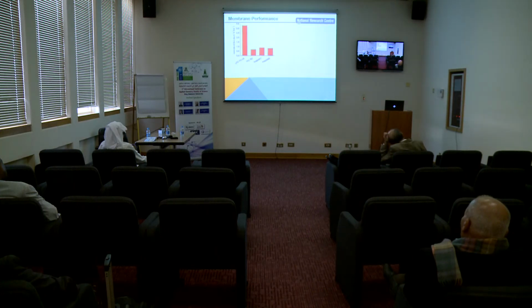The surface properties were also investigated using zeta potential, and here we can see that the membranes with polyamidoamine 1 and 2 have a higher pH value, which means that we have more amine groups on the surface. And we also investigated the contact angle using the air captive bubble method, and we can see that the UTC 70, which is a commercial membrane, has a lower contact angle than the membranes modified with polyamidoamine, which also confirms the presence of more amine groups, or more hydrophilic groups, on the membrane surface.